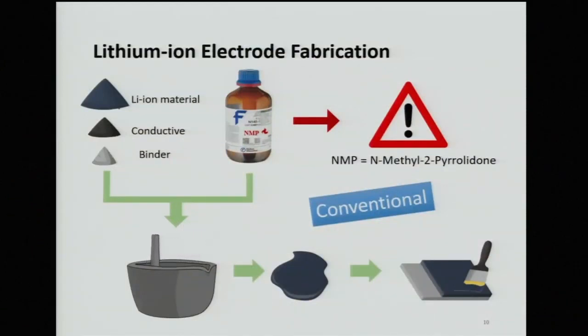You see, with battery materials, we use very small materials. They're nano-sized. And what happens when you put this in a slurry is that it becomes extremely viscous, and it doesn't want to flow right. This prevents it from being able to mix properly and makes non-homogeneous or non-uniform coatings.